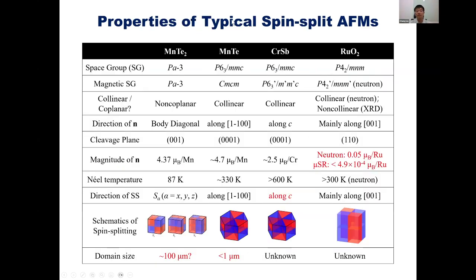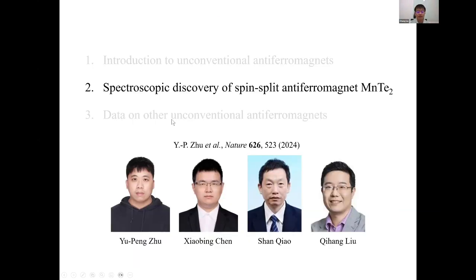So these are the properties of some typical spin-split antiferromagnets. The first one is manganese ditelluride, this is manganese monotelluride, this is CrSb, and this is ruthenium oxide. For example, the size of the antiferromagnetic domains turns out to be very important in the ARPES measurements, since the average spin signal from several domains will be significantly weaker than that from a single domain. Based on our scanning NV magnetometry measurements, we argue that the domain size in manganese ditelluride may be large enough for the detection of a substantial spin signal here.